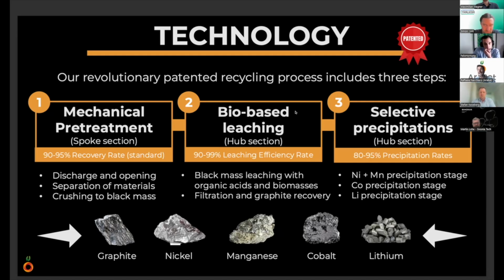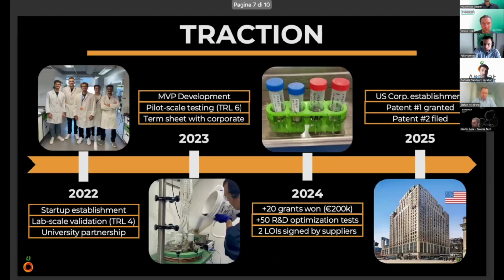Our final stage is a selective precipitation stage where we can recover the nickel, manganese and cobalt, and finally the lithium, in the form of hydroxides, and the latter in the form of carbonate, by changing the pH of the leaching solution. That's our process with a very high performance. For example, we have up to 99% of leaching efficiency capability, and our current performance rates achieve up to 90-95% of precipitation rates of all the critical raw materials that are strategic resources for our countries and continents.